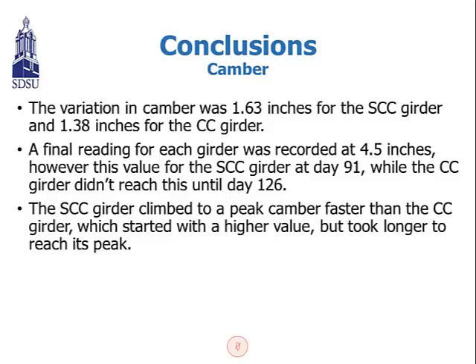And here's the conclusion for the camber. So for the camber, the variation of the camber was 1.63 inches for the SCC girder, while 1.38 inches for the CC girder. And the final reading for each girder recorded 4.5 inches. However, the SCC girder reached this value at day 91, while the CC girder didn't reach this until day 126. The SCC girder climbed to peak camber faster than the CC girder, which is interesting. We start with the higher value, but it took longer to reach the peak.